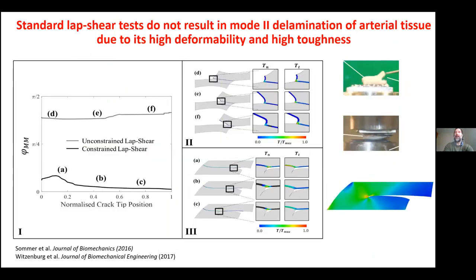So the second way that a crack can grow is through shear. And basically what we do with a shear test is we take the material and we move it like this. So we're basically pulling the two layers apart by moving in the same plane as the crack. And this kind of test has been done for many materials, polymers, composite materials for aerospace, metallic materials. And there have been some efforts to do this on arterial tissue.